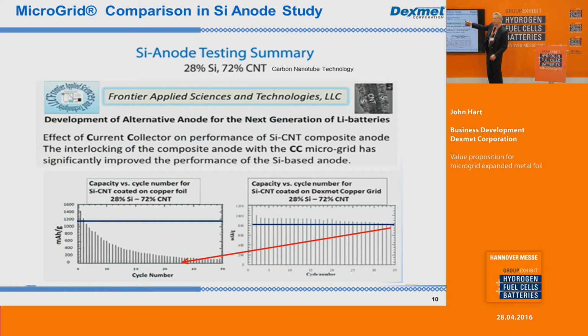They've been working on developing silicon anode, and this is, granted, on a coin cell, so it's a one-layer cell. But what they did is they replicated their control group, which was the basic unit they were using, and they simply substituted our expanded metal foil for the solid foil to see what the difference was. As you can see, it's an extremely profound difference. With the expanded metal foil, after 35 cycles, we've still got more than 80% capacity, whereas in their control, they dropped to 80% after about the 5th or 6th cycle. So this is coin cell R&D work, but it's still very indicative of the potential that expanded foil can offer.